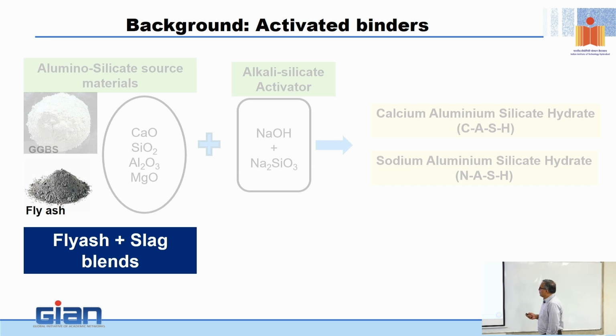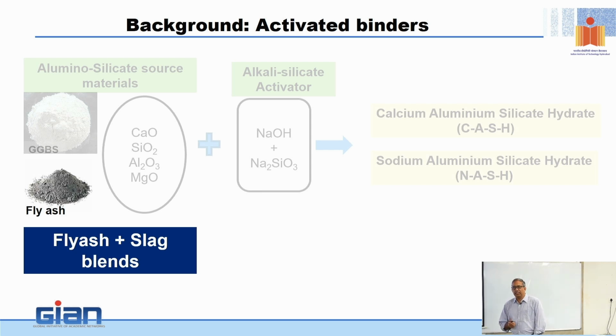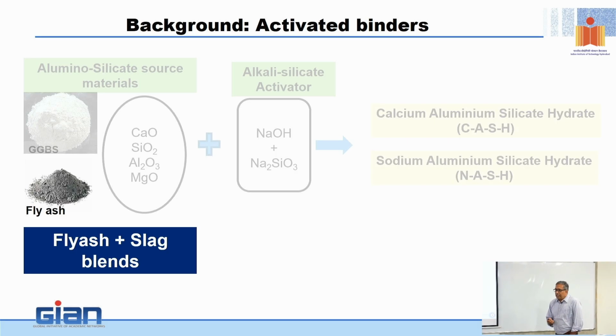Now, when does calcium aluminosilicate hydrate, or CASH, form? When you start with a calcium-rich source, like GGBS, and alkali activate it, what you may form is CASH. CASH is like a distant cousin of CSH. Therefore, calling it a geopolymer is a misnomer. So please be careful. I know people use it colloquially and it's a catchy word, and everybody throws around the term geopolymer, but not all alkali activated materials produce geopolymers. If you really want a geopolymer, you should drop the source that has calcium in it and go with a calcium deficient source. Therefore, when you use only fly ash activated with sodium hydroxide and sodium silicate, you produce sodium aluminosilicate hydrate, NASH. That, in a technically true sense, is a geopolymer.